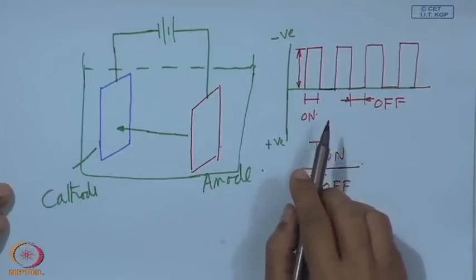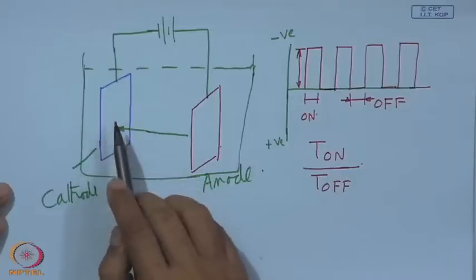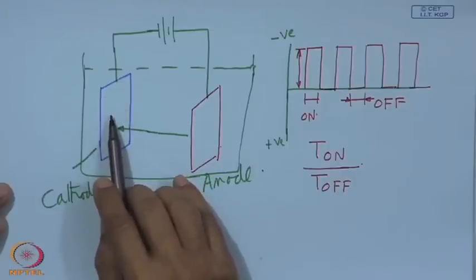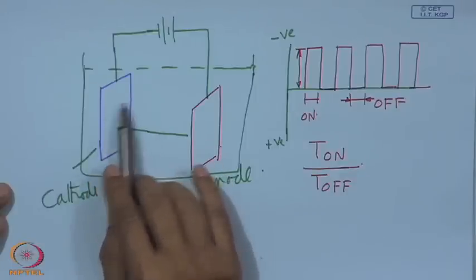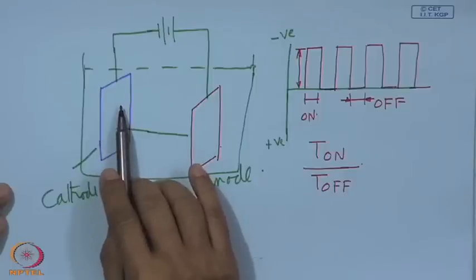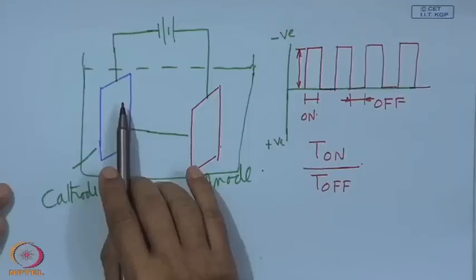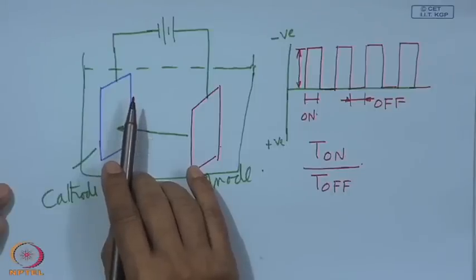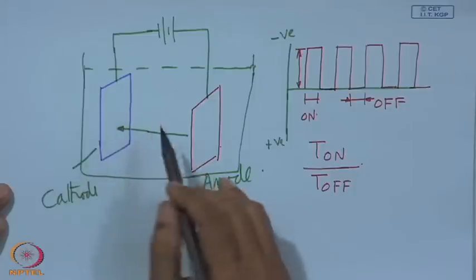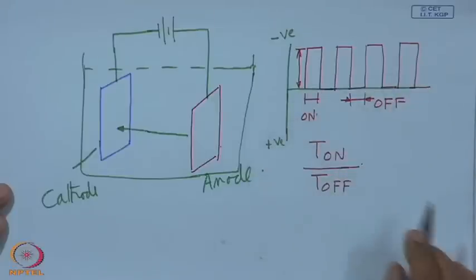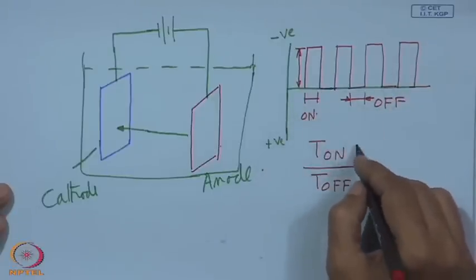By this interruption, we see that the material which is deposited, sometimes there is some unwanted contamination or oxidation in the coating that can be removed or interrupted, and in principle we can recall this pulsed DC type supply in sputtering, whereby this positive pulse cleans the target. That means the target is cleaned by this positive pulsing. Similarly, this is one way of doing it. So, here it is the on and off time that one has to find out.